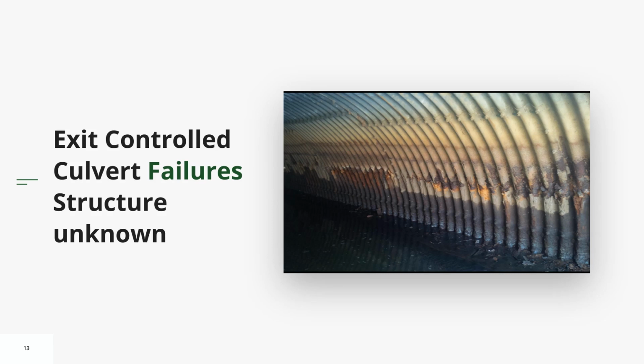So it is just at that band area on the sides, typically 8 and 4 or 9 and 3, that has failed. And in this case, within 150 or 200 millimeters above and below that failure band, the pipe was a full 6 millimeters in thickness. But at that band, it had failed the whole way along. I'm not sure exactly why. It's probably to do with water and oxygen levels.